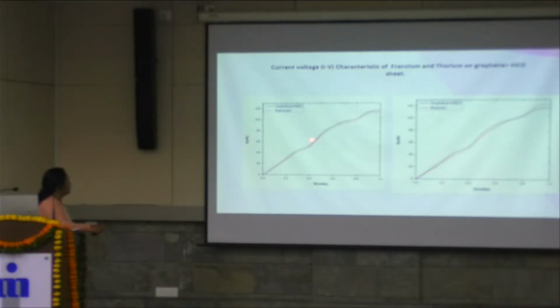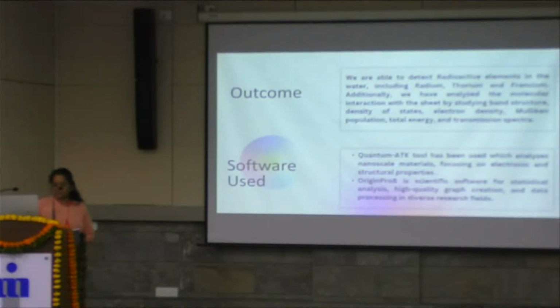The current was decreasing in all the cases, whenever we put the element near the surface of the graphene sheet. So as an outcome, we observed that the graphene sheet was able to sense the radioactive elements, which were radium, thorium, and francium, but not the radon.